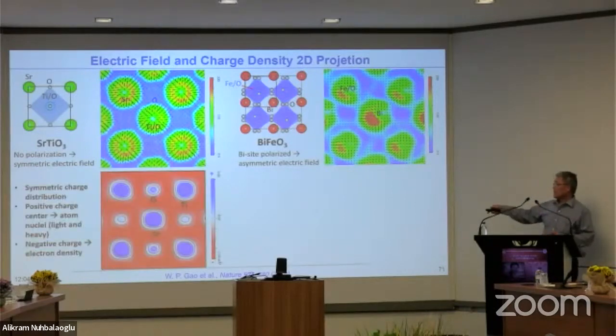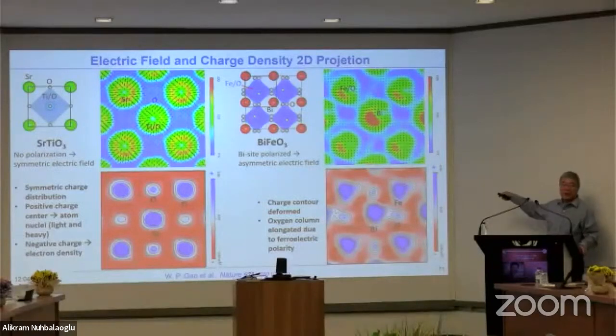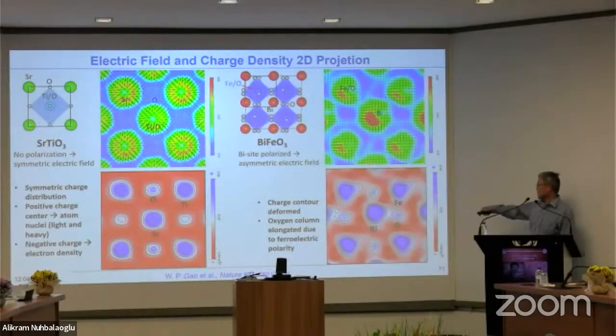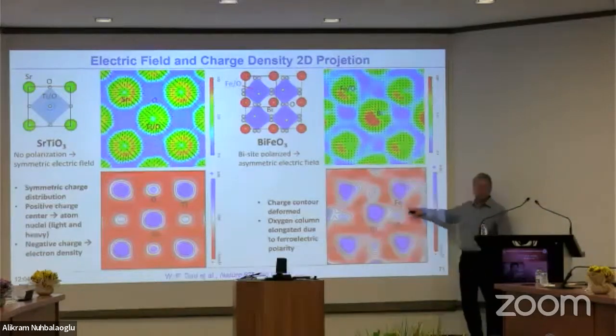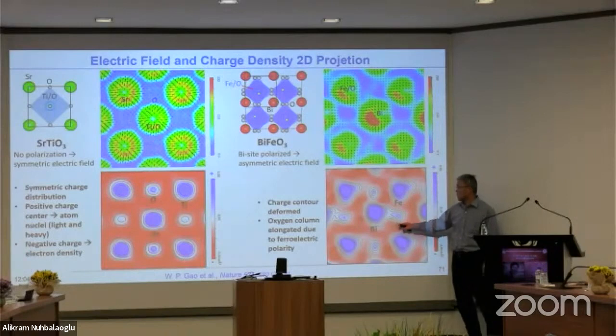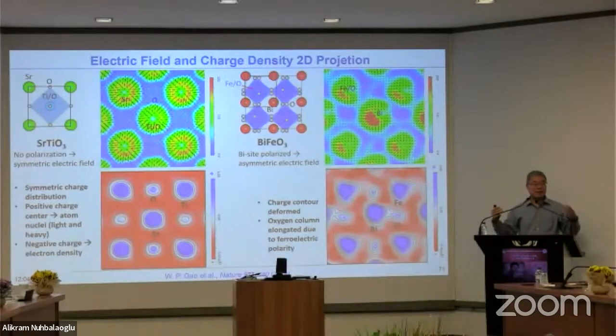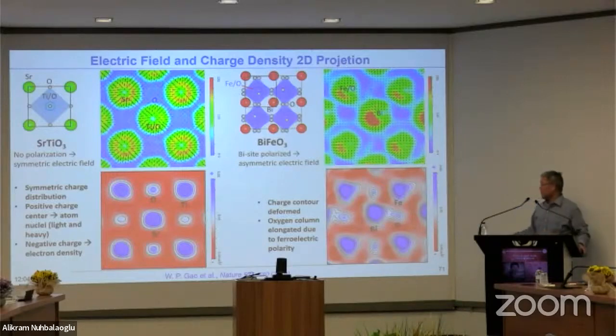Now, if you go further, the divergence of the field tells you the charge density. This is the charge density of strontium titanate. You can see the electrons, which are negative charge in red color, are uniformly distributed around each atomic column. So this is good; this is a pure crystal. But for the ferroelectric, which is polarized, you can see the electron charge is no longer uniform around the column, and it sits on a bridge between ions. This is very important to form a bond. Also, the origin of ferroelectricity in bismuth ferrite is related to the bismuth 6s electron, a lone pair. This will give you a lot of information, but I'm not going to talk about those details, and it is still in the early stage.